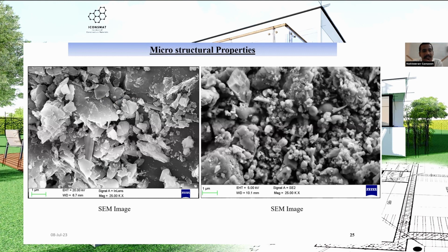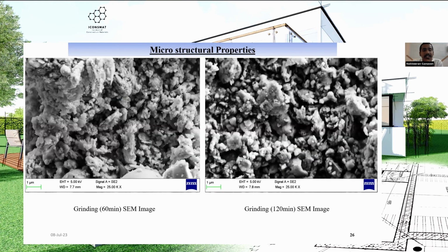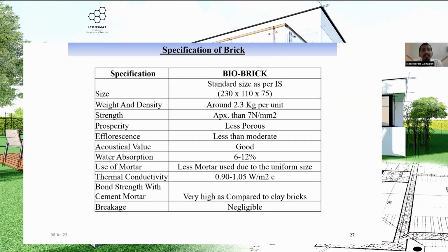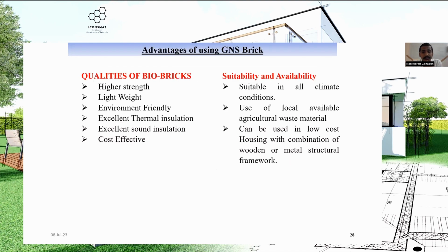These are the microstructure images we get. They show that the bonding between the GNS and the fly ash and hydrated lime is so perfect, and the porosity is very low. This is the specification of the bricks. We achieve durability, weight, low porosity, and low water absorption. The thermal conductivity is so good. It bonds well with the mortar. Everything is achieved in this one.